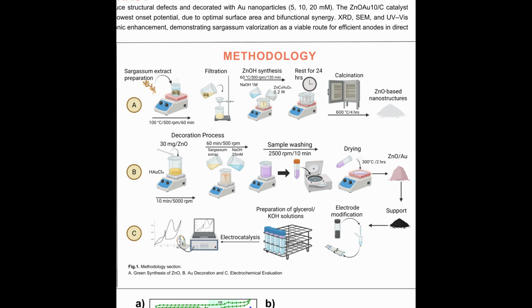Stage B: gold decoration of zinc oxide. The calcined nanostructures were impregnated with aqueous solutions of gold salt at 5, 10, and 20 millimolar. Reduction under controlled conditions anchored the gold nanoparticles onto the defect-rich zinc oxide. Varying the gold content allowed assessment of the trade-off between surface area, particle dispersion, and catalytic performance. Lower loadings favored fine, well-distributed particles. Higher loadings risk agglomeration and site blockage.